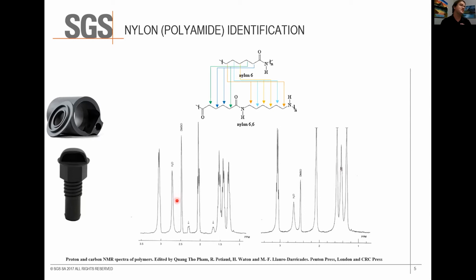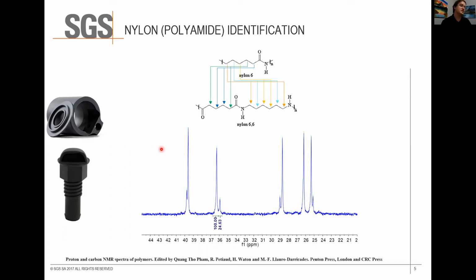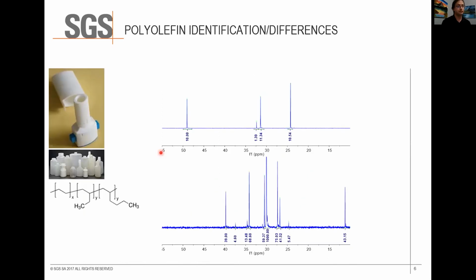If we know one of these is nylon 6 and one is nylon 6,6, you can reasonably well discriminate them. But people like to blend these two polymers together, so we may be looking at what the actual amount of each is. Carbon NMR works quite a bit better for nylons - here's a blend of nylon 6 and 6,6. Carbon NMR has just enough separation for you to discriminate and identify which one you have, and also what the ratio is if it's a blend, which frequently it is.